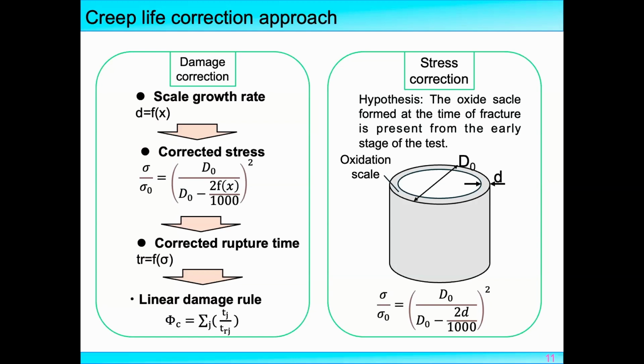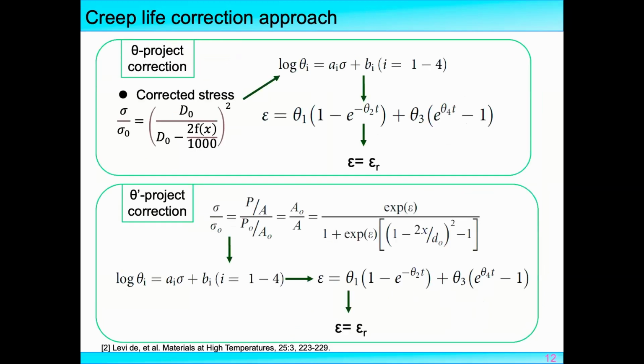This method is usually used in miniature test series. It's called the stress correction. Here we assume that the oxidation scale formed at the time of fracture is present from the early stage of the test. So we only correct the real stress without considering other parameters. And the third one we call the theta projection correction. We can use the theta projection method to represent a creep curve here by correcting the stress and substituting it into the theta projection method.